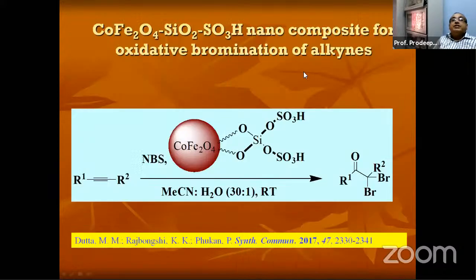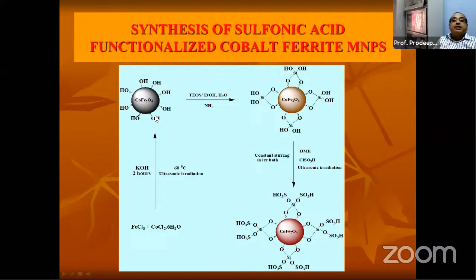And here we changed the surface property. We already have this silicon, this oxygen, this kind of bond. And what we did, chlorosulfonic acid we have used, then surface functionalization we have done. Then we have used this catalyst for oxidative bromination. So this is the reaction, this is the synthetic method.